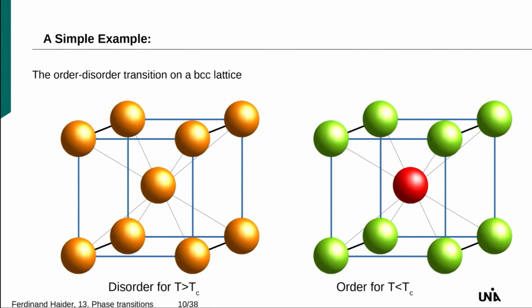This order, no, there are more things, but briefly. This order-disorder transition, because this is a nice example which one can easily treat without these ad hoc assumptions in the Landau theory. What comes out is very similar, but it's a bit more a microscopic picture than this Landau theory. So that's this case I already described. The body-centered cubic lattice, for example, in beta brass, copper zinc. So below the transformation temperature, you get this type of order, which is called B2 structure, at least in one of the many terms to denote different structures.